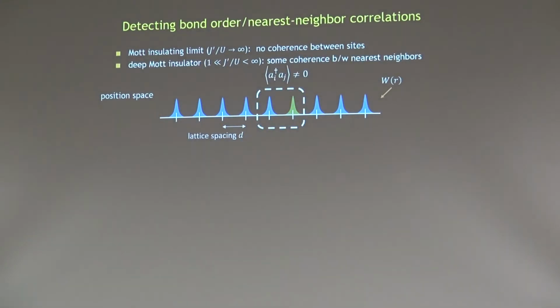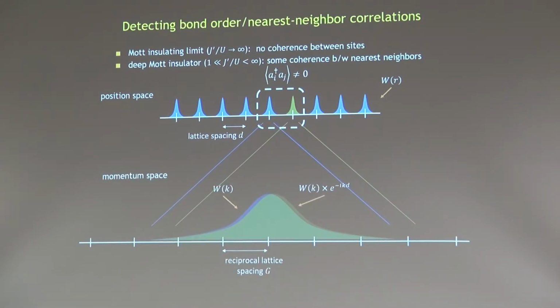Now, in contrast, what happens if you go away from the deep Mott insulating limit to where you have, let's say, just the start of coherence within the lattice, which is to say, just nearest neighbor coherences? Let me focus on what happens if there's a little bit of coherence between 2 neighboring sites in the lattice, characterized by this coherence function being non-zero. Now I look at the diffraction again in momentum space. The atoms in this blue site expand like a big Gaussian. The atoms in this green site also are Gaussian in momentum space.